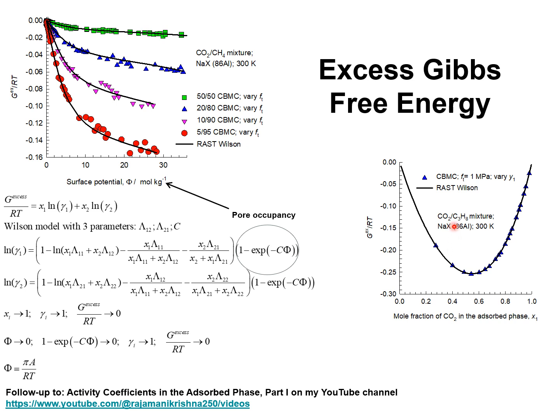For CO2 propane mixture adsorption at a temperature of 300 Kelvin, I had shown configurational-bias Monte Carlo simulations conducted keeping the total fugacity in the bulk phase constant at 1 megapascal and varying the composition of the bulk gas phase mixture. The excess Gibbs free energy divided by RT is a function of the mole fraction of CO2 in the adsorbed phase mixture.